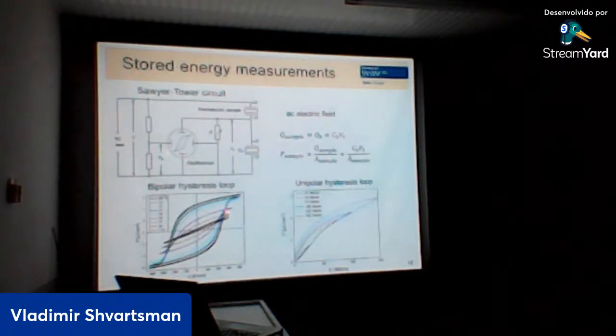So how can we measure this stored or recoverable energy? Typically people use the Sawyer-Tower circuit to observe the polarization hysteresis loop, and sometimes people analyze bipolar hysteresis loops, and from the area between the charge or discharge curve they estimate the corresponding energy density. More correct is to use the unipolar hysteresis loop, where the electric field is cycled only from 0 to the maximal value.